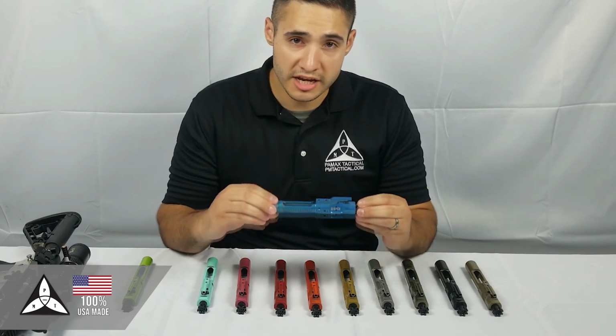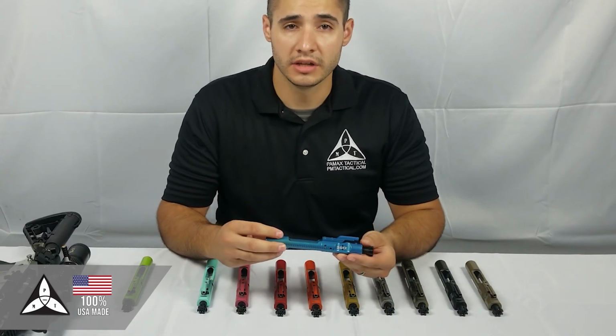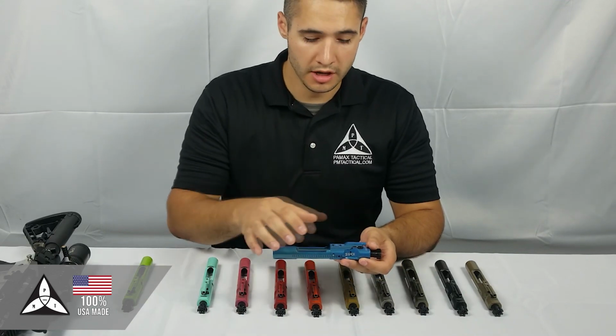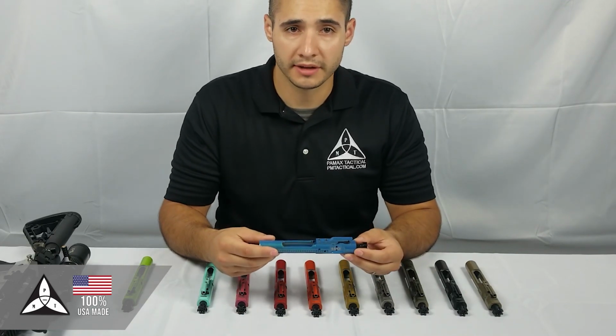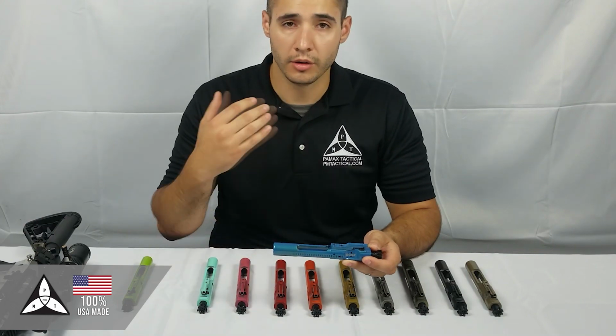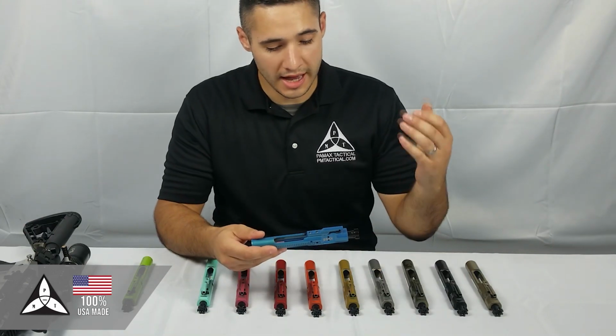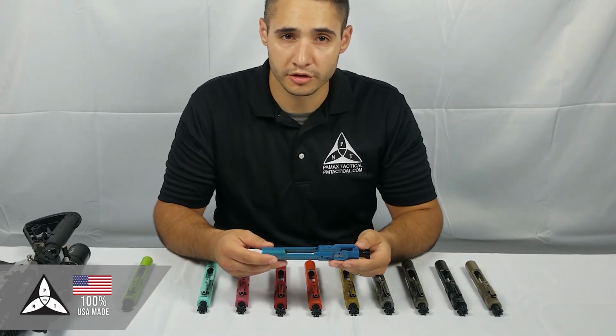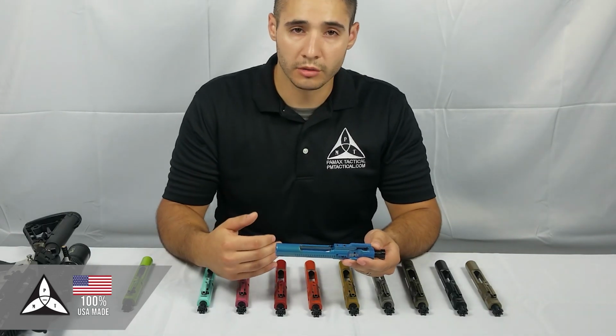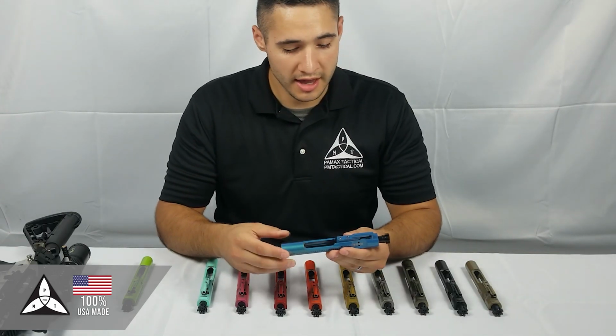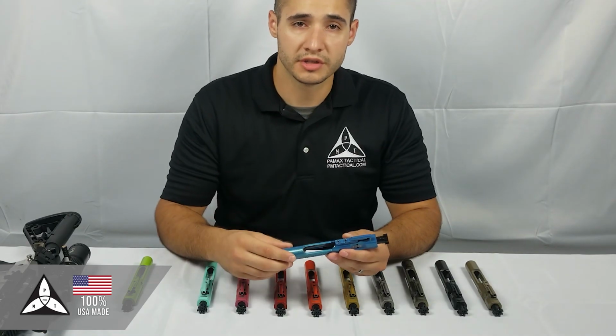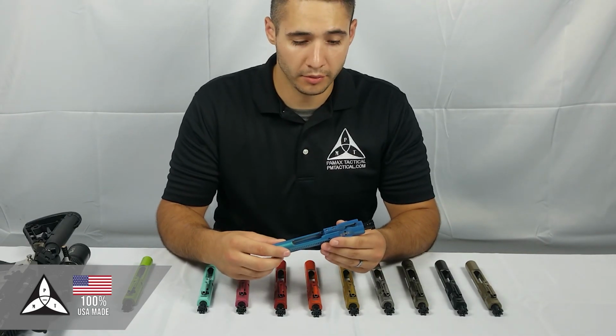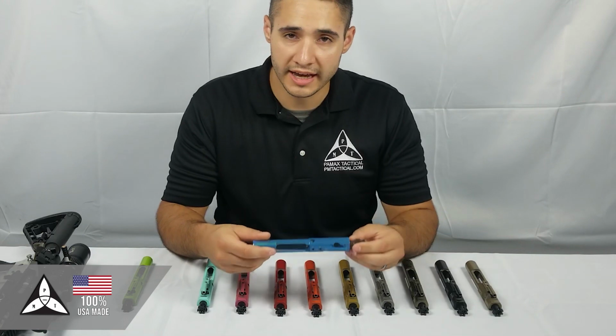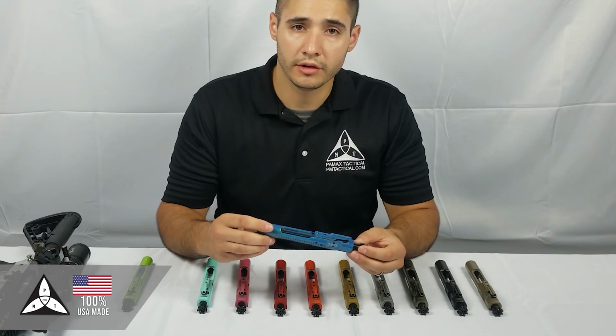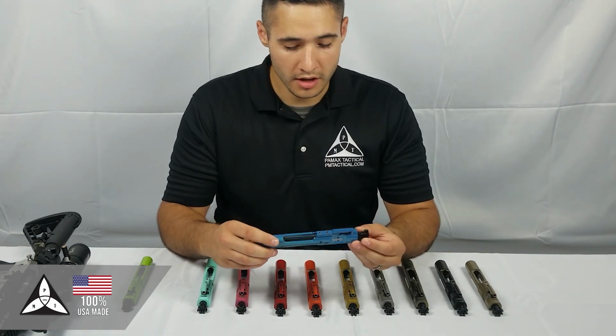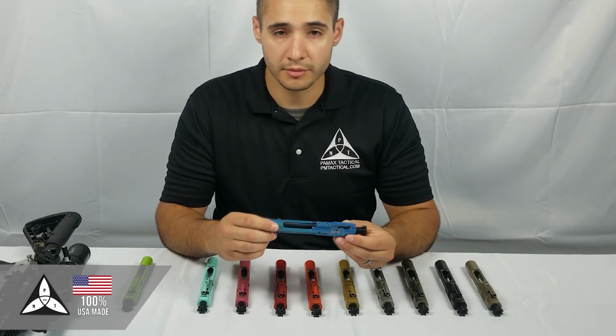You're going to be able to recoat your bolt carrier group to maximize the warranty we offer with the bolt carrier group. Be able to recoat that carrier time and time again for a minor surcharge rather than have to go and buy another bolt carrier group. It's going to have a higher temperature operation at 1200 degrees compared to a much lower threshold nickel boron bolt carrier groups. And you're going to have 4 times more corrosion resistance with our XSlick coating compared to nickel boron. The life cycle of the coating, again, is usually around 6,500 rounds before recoat is required. But that's in a nutshell what the pros and cons are between the two.